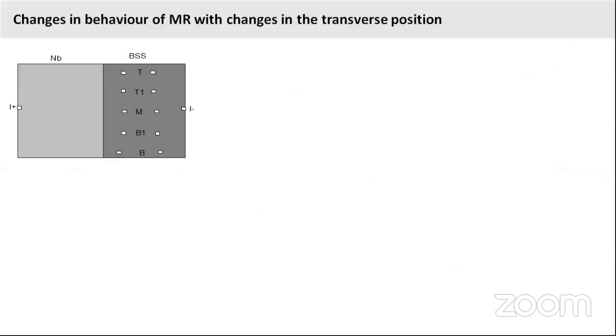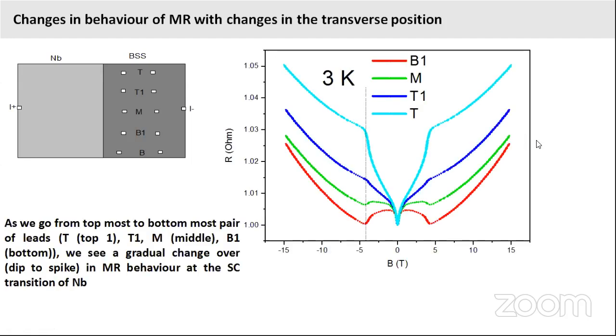So to try and understand this further, what we did is we made leads across the entire width of the topological insulator. If you remember, this is the niobium covered portion of the TI, and this is the pristine TI, I mean, the TI without a niobium covering. So we tried to make contacts across the width of the topological insulator, and we tried to see how the variation happens. And this is a striking result that we observed.